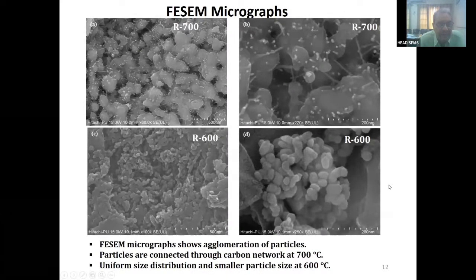This is the SEM picture of the material which has been synthesized at 600 degrees centigrade and 700 degrees centigrade. The important part for us to understand here is the different features. People do talk about phases, but I always talk about the features. You can synthesize the material, you can even produce a very fine size of the material, but features become very, very important.